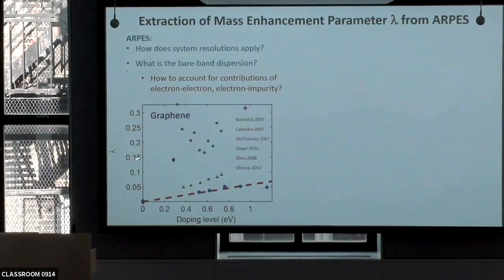So here is the lambda, the electron-phonon coupling, extracted in a number of papers, and you can already see the spread in these values. These are as a function of the doping level for the graphene itself. And there are many reasons for this mismatch, but certainly one clear reason is resolution effects. Apparently this cloud of data, when interpreted taking into account resolution, can be pushed down to a value which is much closer to the DFT number.